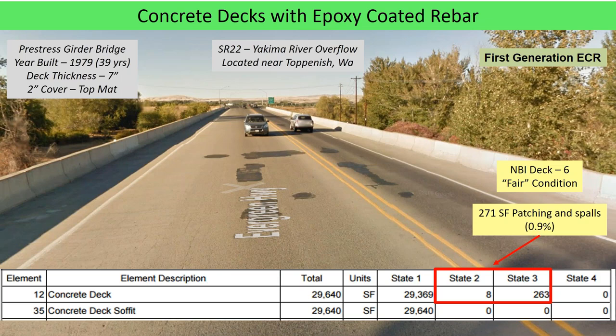Here's one of the first ones. It's over in the Toppenish area on SR22, and you can see quite a bit of cracking in the deck, and then maintenance has done some patching, and then the inspection has noted that. So we have nearly 1% of the deck is now patched or spalled. So this will require some type of an action over the next 10 years.